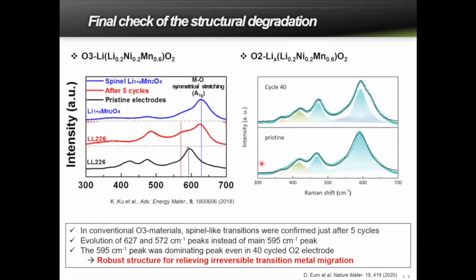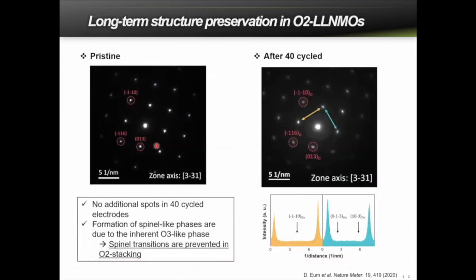And this reversible migration of transition metals also inhibits the unnecessary formation of disordered or spinel-like domains in the structure, as can be seen from this Raman spectroscopy. Moreover, the structural stability could be maintained even after long-term cycles, without any signatures of disordered or spinel-like formations.